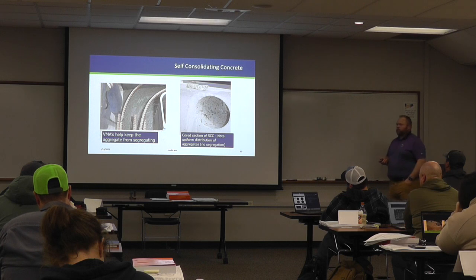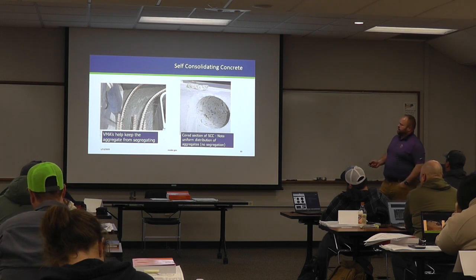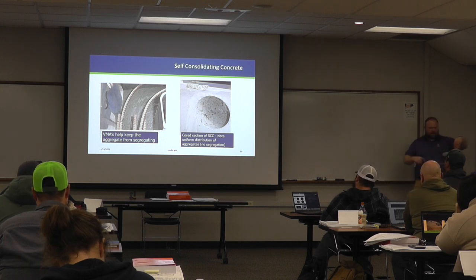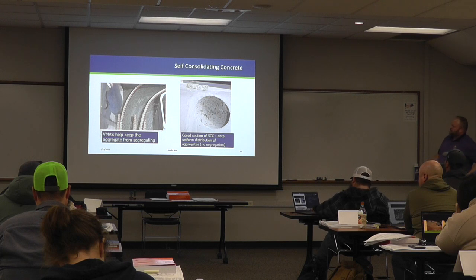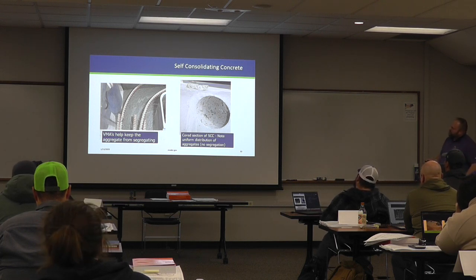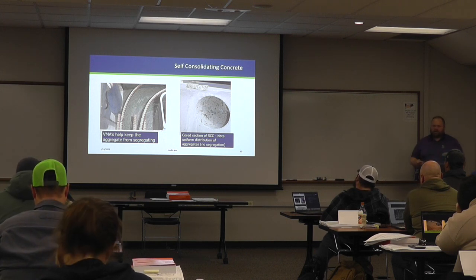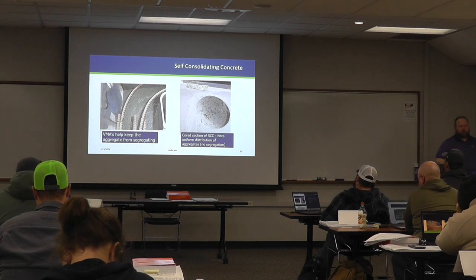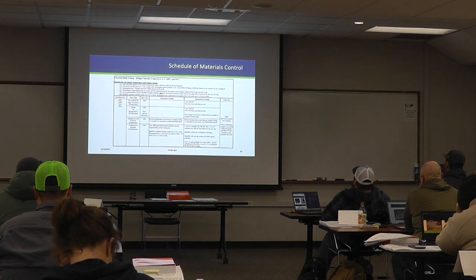This was a trial pour for the Hastings Bridge. They put up some formwork. They had rebar and a corner to go through. They placed the concrete on one side of the form and it filled up the rest of it. And then afterwards, once the concrete was hardened, they cut a core out of it. And you can see you've got good dispersion of the coarse aggregate throughout that, even around the rebar there. So SCC, when designed properly and placed properly, is definitely a tool to use in the toolbox here.